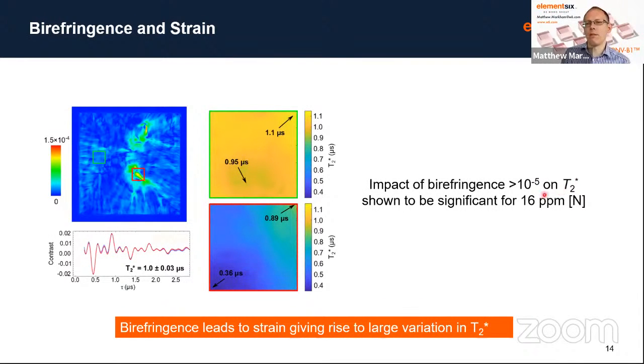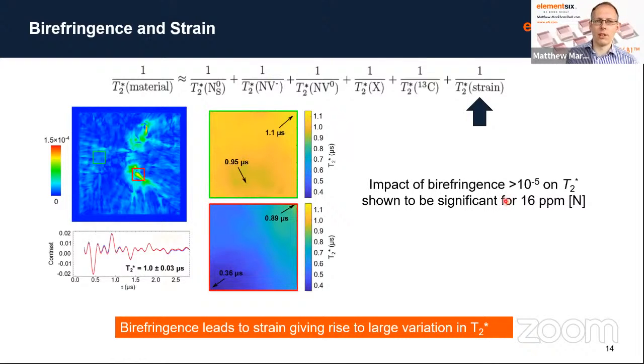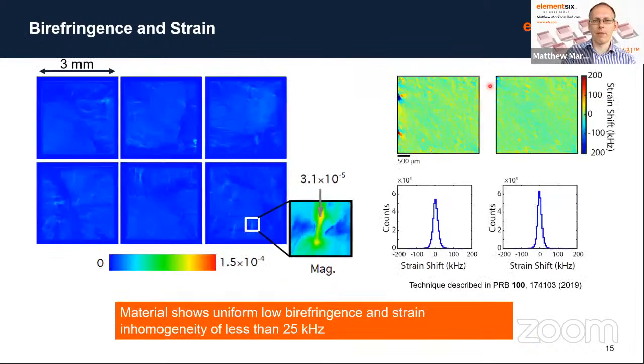So the impact on birefringence: in this material, if the birefringence is greater than 10 to the minus 5, we get this variation in T2 star. And that, as I said earlier, comes from this parameter here.